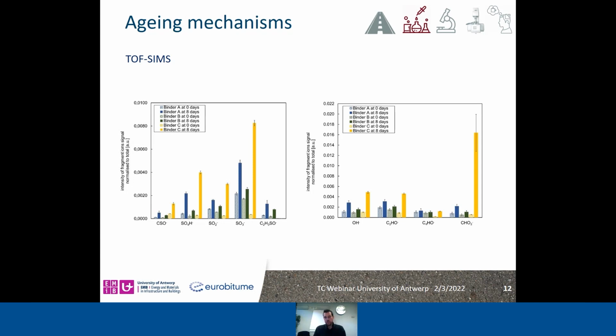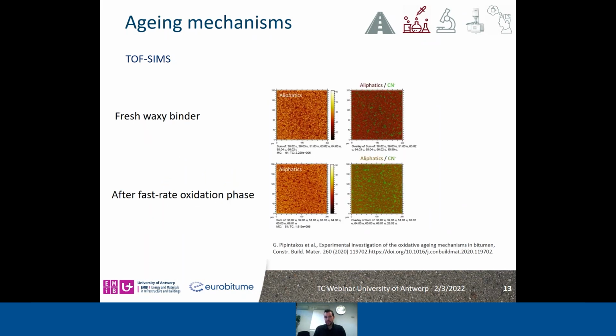With TOF-SIMS, it is also possible to extract from this bitumen surface that we bombard more information, like high-resolution images. High-resolution images, especially for one of the binders that was used, binder C, showed a clear difference before and after the fast rate phase. Here you can see the high-resolution images of this binder, which showed some clear differences in terms of chemical mapping, and more specifically the aliphatics in the bitumen surface were less pronounced after the fast rate oxidation phase. This fact triggered us to investigate more binders after aging, and more specifically to focus on the bitumen microstructure triggered by these chemical differences in the surface microstructure.